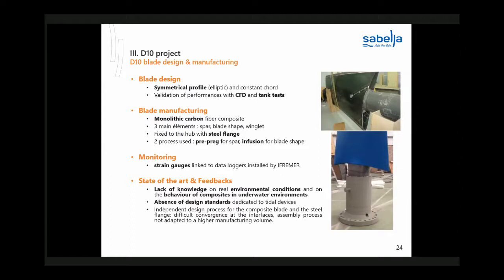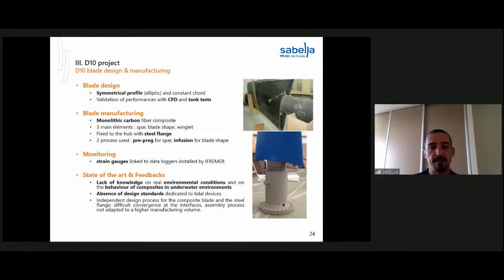Regarding the feedback on the D10 blade design and manufacturing, for the blade we chose a symmetrical, elliptic profile and a constant chord, so that we can produce energy without turning the machine and pitching the blades. We validated the performances with CFD calculation and tank tests. For the blade manufacturing, we use monolithic carbon fiber composites. The blade is composed of 3 main elements: a spar, the blade shape, and a winglet at the top. The blade was fixed to the hub with a steel flange, and we used 2 processes for the carbon composite: pre-preg for the spar and infusion for the blade shape.